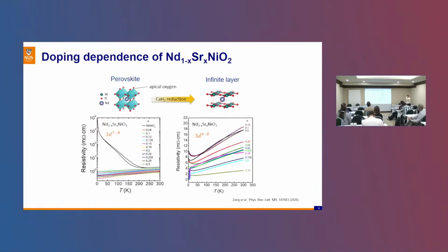All right? And within half a year or so, we were able to reproduce this system. Then we developed the doping dependence of these Nd-based nickel superconductors. As you can see, the left one is the resistivity of the perovskite structure with the metal-insulator transition in the parent compound. Then as you dope, it becomes a metallic system. As I said before, for doping around 0.1 to 0.25, we have been able to produce transitions from a very low few Kelvin up to 15 Kelvin transition temperature.